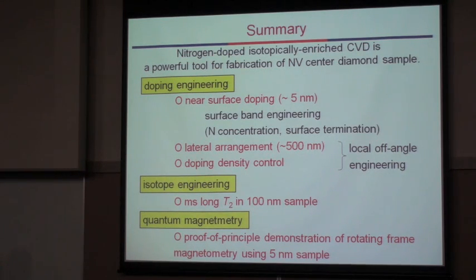And we also demonstrated the lateral arrangement and doping density control by using the local off-angle engineered substrate. And also, I showed the isotope engineering is so important to obtain the long coherence time. So finally, we demonstrate the quantum magnetometry using a spin locking system and our 5 nanometer thickness sample. Thank you very much for your attention.